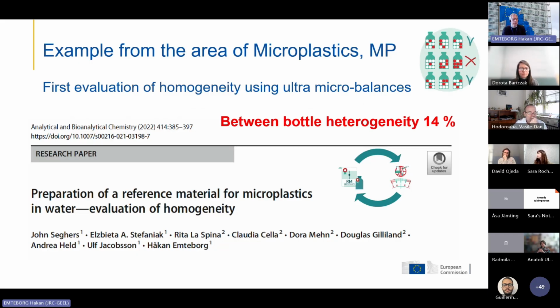Now I come back to this RM method causality dilemma, because when we evaluated those first attempts of preparing the salt cake, we had only access to a home-devised method using ultra-micro balances, where we actually weighed the amount of microplastic particles that was embedded in these salt cakes. And there, using that technology, we found a between-bottle heterogeneity of 14%. So that was a rather rudimentary method, but that was the only thing we had available for fast checking in-house. So that's why I put that circle of the RM method causality dilemma there.